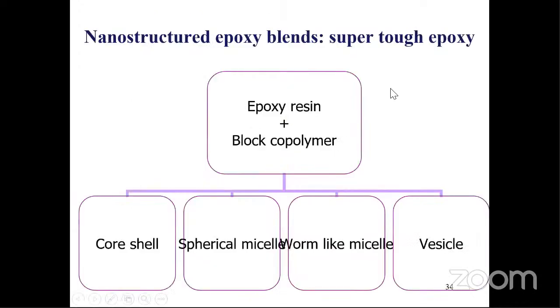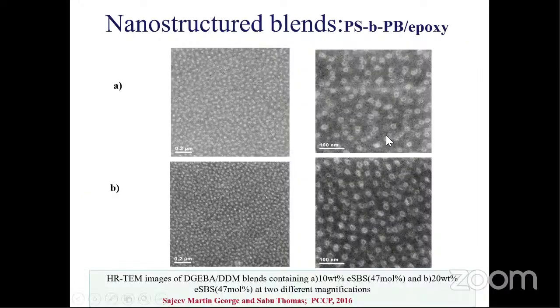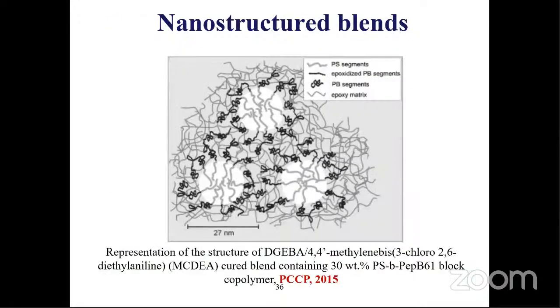So what we did is we mixed epoxy resin with block copolymers of different molecular weights and different compositions. If you blend them intelligently, you can make core-shell, spherical micelles, worm-like structures, and vesicles. I will show you just a couple of slides. A PhD student of mine mixed epoxy resin with styrene-butadiene-styrene triblock copolymer, where the butadiene part has been epoxidized. When we do that, look at the nanostructures we have developed. We have developed beautiful nanostructures. And that gave rise to good impact modification.